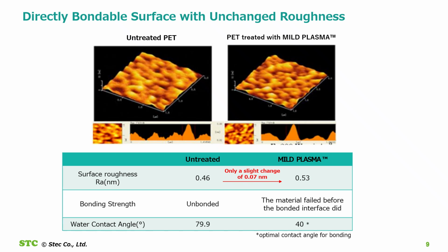Also, as shown here for PET, the water contact angle changes significantly, from 79.9 degrees to 40 degrees, while the surface roughness changes only slightly, from 0.46 nanometers to 0.53 nanometers. In other words, we can create a bondable surface without sacrificing surface smoothness.